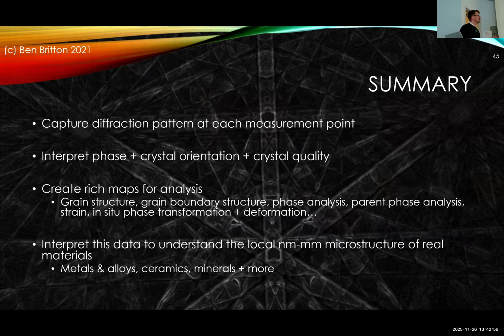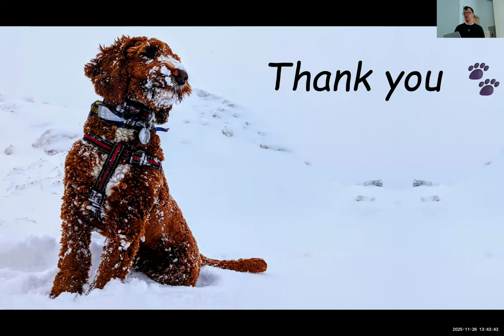So to summarize, hopefully what I've shown you is that EBSD is just an embarrassingly parallel problem in that we collect a diffraction pattern at each point. But perhaps what's most ingenious about the technique is it's interpreted live. And that really increases your access to useful information. We interpret the phase, orientation, and crystal quality to build up rich microstructural maps. And these can show things like grain structure, grain boundaries, phases, parent phases, strain, in situ phase transformations, deformation, and more and more. We can interpret this data across multiple scales between nanometers and millimeters to look at real materials. And we've used this, as I've shown, in metals, alloys, ceramics, minerals, and a whole range of other crystalline structures. With that, thank you very much for your attention, and I welcome questions.